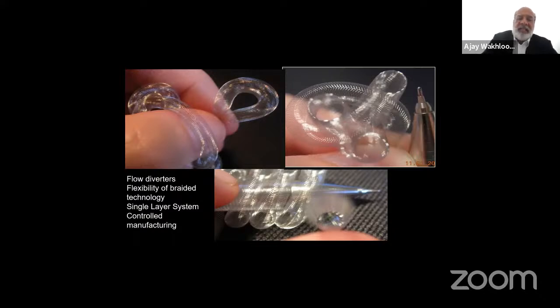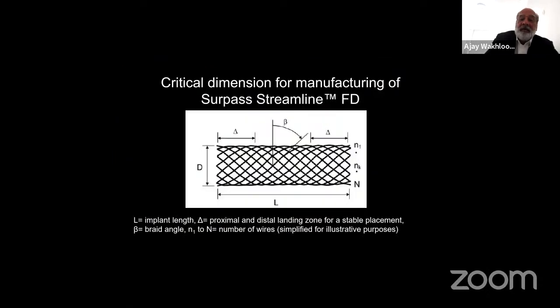So we came up with this idea of using the mini version of the Wallstent, you would say, using various braiders here. And then we defined the different parts of the braiders. And you see here, the most important thing to remember is the braid angle, which is here indicated by beta, but also the porosity. And then I will come to the term of mesh density and the size of the cells, which are around 350 to 400 microns to allow the endothelium to go over it. Then there are other parameters like the diameter and length of the device. That's important for you in the clinical setting.